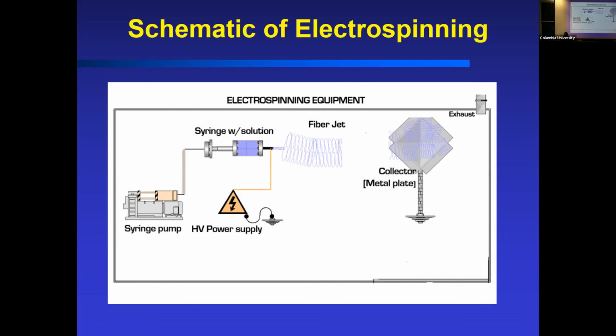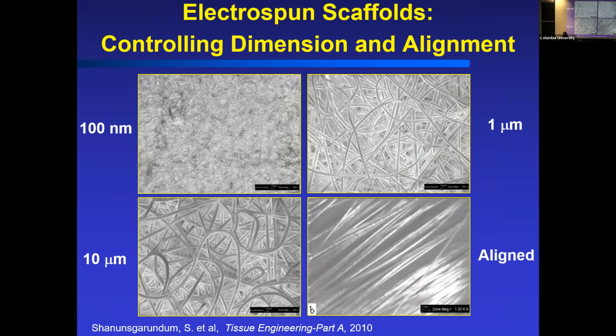That solvent, or polymer solution as it's being ejected at a certain flow rate, is charged, and it results in the solvent being evaporated, and you get these fibers. And these fibers can be, again, depending on parameters used, we can control dimensions on that. So small nanometer up to fairly large micron scale dimensions, as well as orientation.